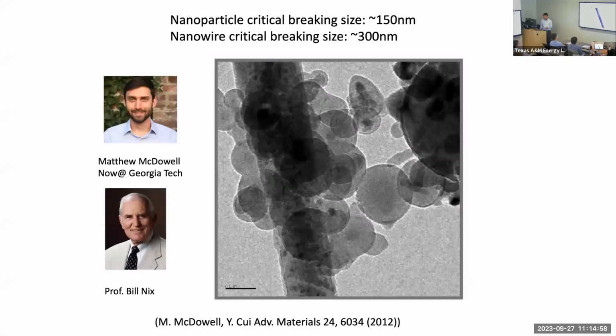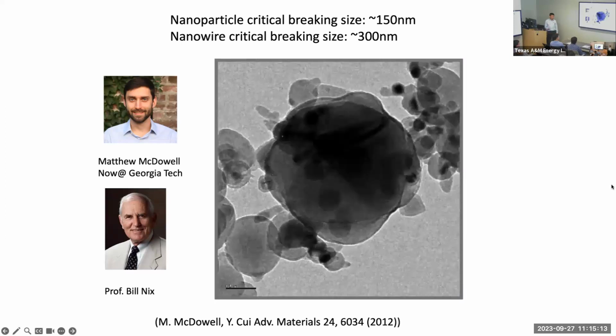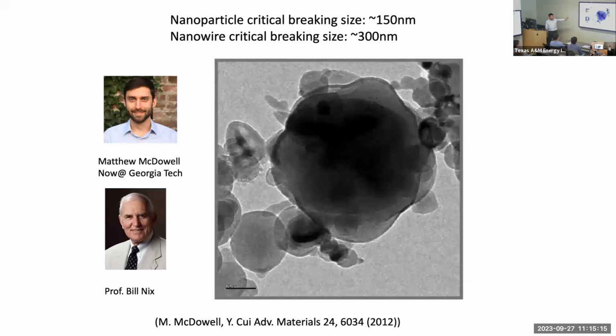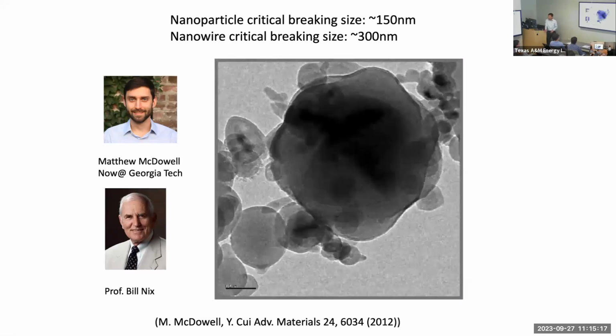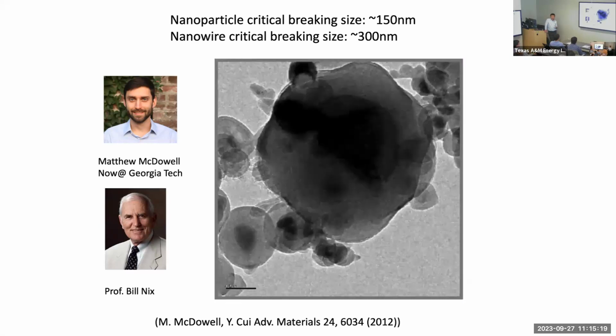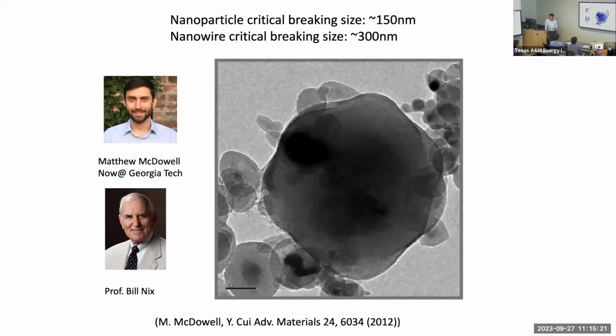If you go look at the particle, one question is, what's the critical breaking size below which it doesn't break, above which it will break? So we want to figure out this critical breaking size. In the middle of the screen, that big particle is 800 nanometers to start with.